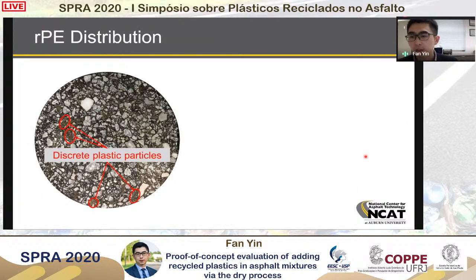This is a picture of the gyratory specimen that we made in our lab, and we just used a wet saw to cut it into pieces and look at the cross section. As we can see here, there's lots of discrete plastic particles that stay outside the binder phase. So we know, just looking at this picture, not 100% of the plastic goes into the binder. And the reality may be that the majority of the plastic stays outside the binder.